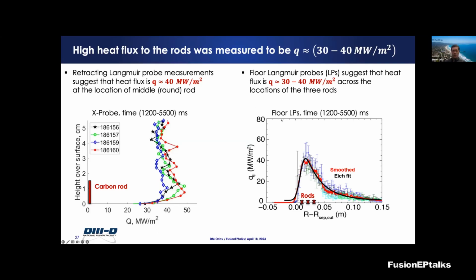We also measured the heat fluxes on the surface using the floor Langmuir probes. These are fixed length probes positioned over the surface. By doing plasma sweeps back and forth before exposure, we could collect the information and construct the profiles.